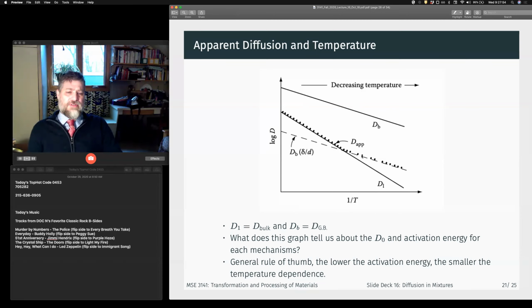This is a trend that you see over and over again: in general, the lower the activation energy that something has, the smaller the temperature dependence it's going to have, right? One place where this rule comes in handy is thinking about the temperature dependence of deformation in different crystal structures. FCC crystals have 12 independent and degenerate slip systems: the 111 planes along the 110 type directions. My close-packed planes and close-packed directions in FCC are my slip systems. It's really easy to move dislocations along those directions.